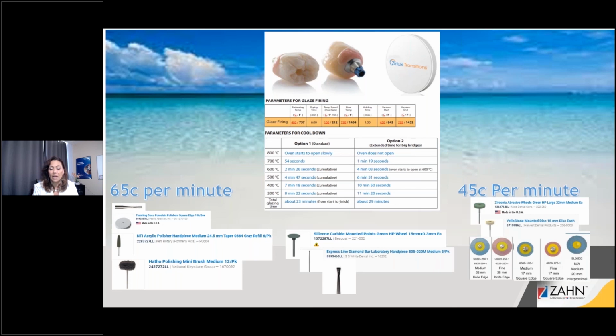Once you create that little score in the zirconia, it's kind of like scoring a tile, and eventually it's going to crack. And the more that we fire it and heat it up, that crack will grow, which leads me into the glazing process. Usually that's an area where you will see fractures, and it's not necessarily because the person glazing it did anything wrong. It's that we started a fracture well before it even got to glazing. So we want to avoid those problems altogether.